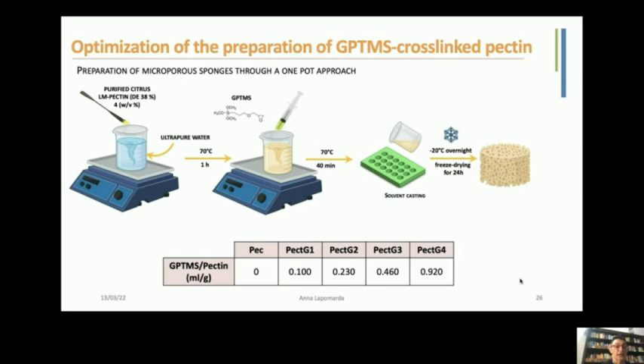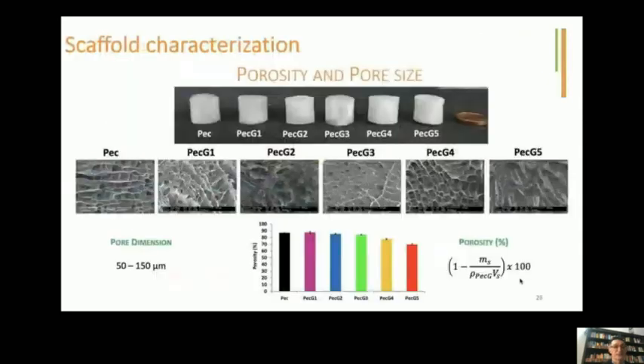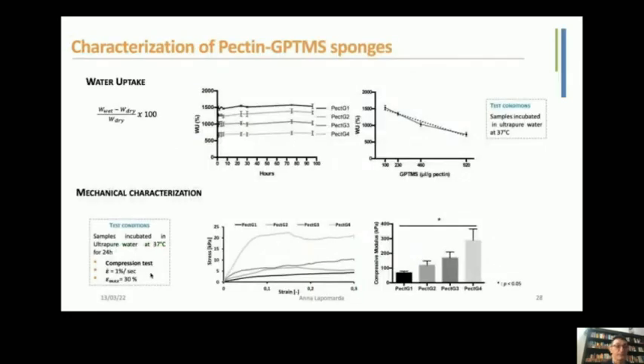As you can see here, we tried different ratios between GPTMS and pectin in the scaffold. And you can see here that changing the ratio from pure pectin and increasing the quantity of cross-linker, the porosity decreases. And the range of these pores is between 50 and 150 micron. We analyzed also the water uptake of the scaffold, and we can see that increasing the quantity of GPTMS it decreases, because obviously the porosity of the scaffold also decreases, and instead the mechanical properties increase as we increase the quantity of cross-linker, so of GPTMS.